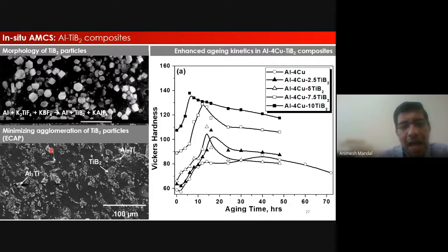Similarly, if you have different amounts of these particles in, say, an aluminum 4 copper alloy, for example, this is the aluminum 4 copper alloy, and these are four different composites with different weight fractions of titanium diboride. So here, what the plot shows you is this. Let us first have a look at the aluminum 4 copper alloy. So the round dots you can see, this is the plot.